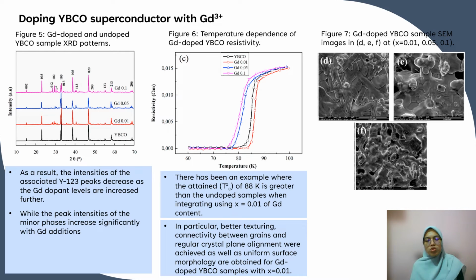Second, doping YBCO superconductor with Gd3+. Figure 5 shows the Gd doped and undoped YBCO sample XRD patterns. As a result, the intensity of the associated Y123 peaks decrease as the Gd dopant levels are increased further, while the peak intensity of the minor phase increased significantly with Gd addition.